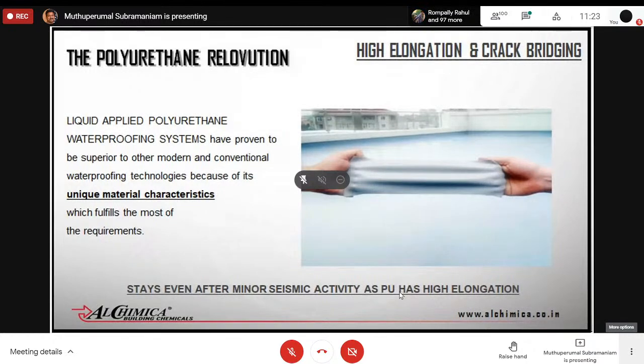The main advantage of polyurethane is that it works without any reinforcement, unlike a bitumen membrane. In bitumen membrane, you need a reinforcement like geotextile or fiberglass mesh, which limits the elongation of the membrane. Whereas in polyurethane technology, the tensile strength of the product itself is quite high, and the elongation is not limited by reinforcement. We have some polyurethane products which have more than 2000% elongation. Because of this property, any cracks developed in the building due to thermal expansion or thermal stress can be bridged, as this coating can expand.